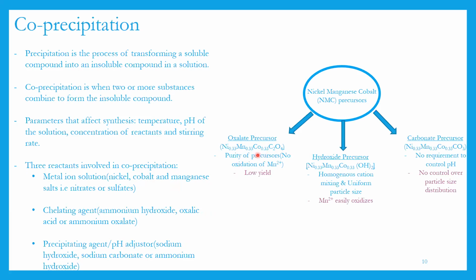With oxalate synthesis, the benefit is the purity of the precursor, since there is no oxidation of the manganese ion. What happens specifically in hydroxide synthesis is that they normally synthesize this material at a high pH, so the manganese hydroxide that precipitates out can easily oxidize. And so the final material that you get has a manganese oxide impurity. I will show you in a second what it looks like.